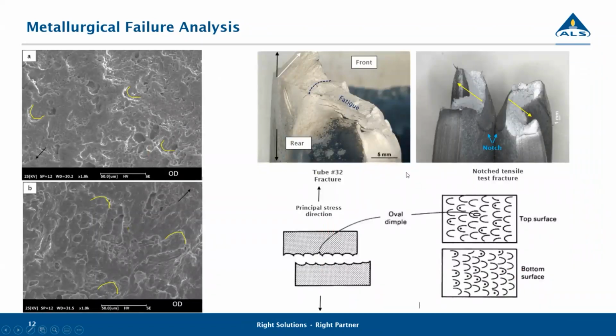So the big question for everybody was, why did it rupture? Initially it was thought that there was an overload event that happened in conjunction with this failure. So we had to first determine whether it was a ductile failure of that final fracture that occurred. When we looked at the fracture surfaces, this is the area where it fatigued and the fatigue crack grew, and then the last portion sort of just sheared off.